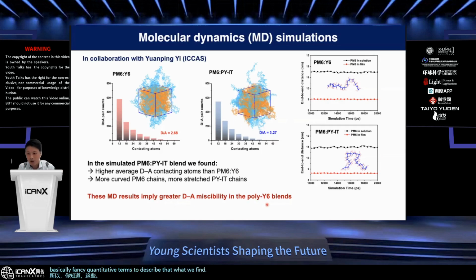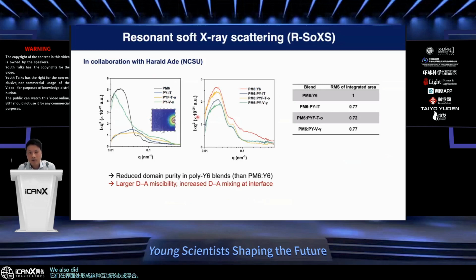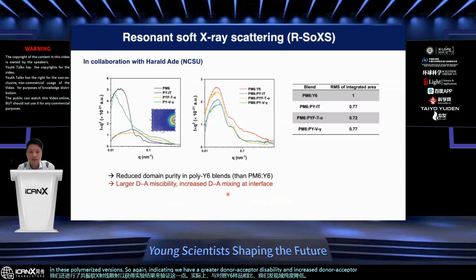What we find is that when we polymerize the Y6 acceptors, the donor-acceptor miscibility is improved. So that would enable them to form this interlocking morphology or intermixing at the interface. We also did resonant soft X-ray scattering to get experimental results to verify this. And indeed, compared to the control Y6 sample, we find a decreased domain purity in these polymerized versions. So again, indicating we have a greater donor-acceptor miscibility and increased donor-acceptor mixing at the interface.